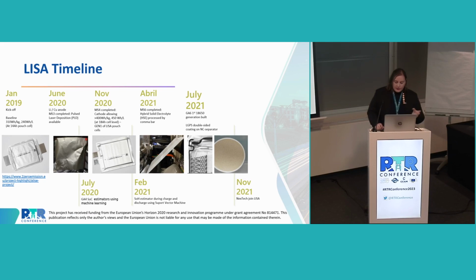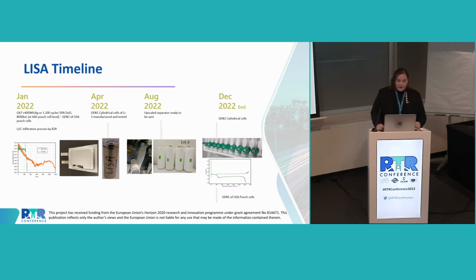Then through the entire 2021, we lost Oxis Energy, but Nextech joined, and we were able to develop our first hybrid solid electrolyte on top of the separator, and we built our first generation of cylindrical and pouch cells with Varta. Then in January 2022, we reached 1,200 cycles at 50% depth of discharge, with more than 400 watt-hour per kg. So we reached 2 of our other KPIs. We built our next generation of cylindrical cells, and until the end of the project, we upscaled this hybrid solid electrolyte to be able to build the new generation of both cylindrical cells and also pouch cells.